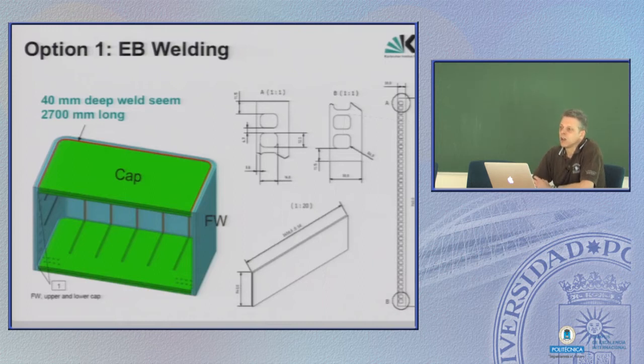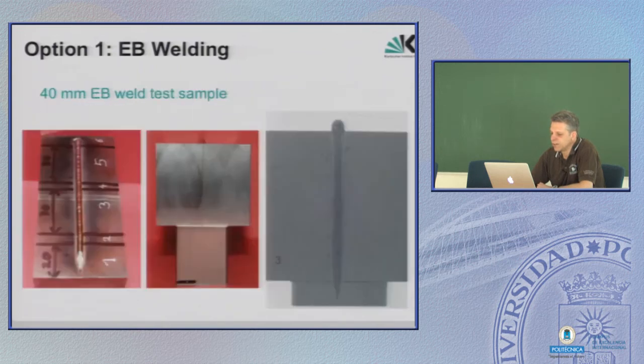First thought again was, well, let's use electron beam welding. This we already knew worked pretty well in all these simple sealing cases. And what we have done, we went to industry, they have really big machines and electron beam facilities where you can perform 40 millimeter deep welds in steel. You see it here: this is the top, the beam comes from that direction, and in the end it produces a weld between those two plates. This was the arrangement, two plates together. At the bottom we have put a beam stopper for some reasons, and in the end it looks fine.